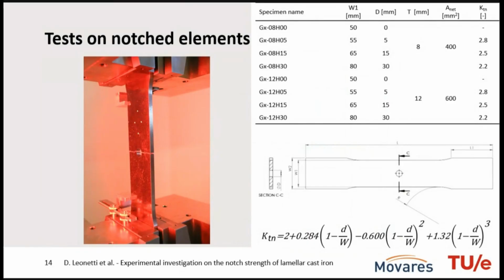So then we made a second test series with specimens that look like a tensile specimen, a bit bigger, with a notch in the center, a simple hole, and the specimens are made such that the net section area is constant. Because we are in a Eurocode-driven kind of approach, you calculate the net section stress and multiply it by the ultimate tensile stress in the net cross section as a failure criterion. So we kept this constant in such a way that the theoretical stress concentration factor ranges roughly between 2.2 and 2.8. We're a bit limited by the dimensions.